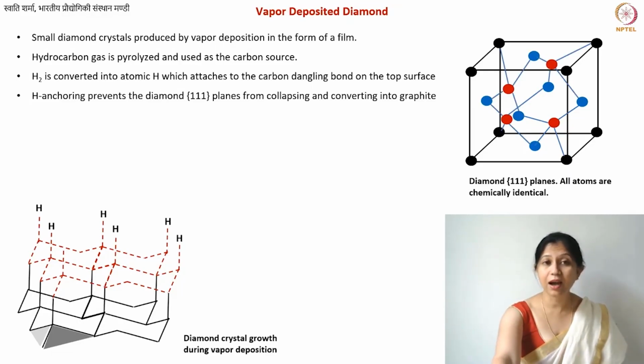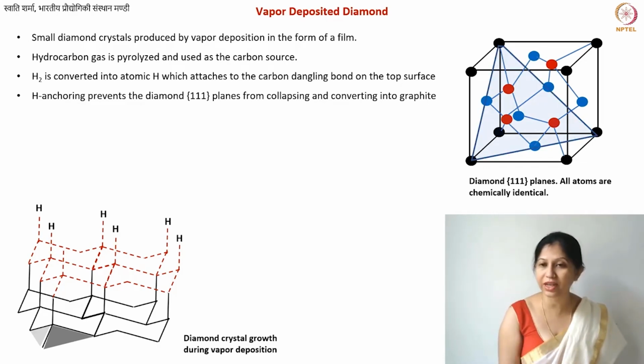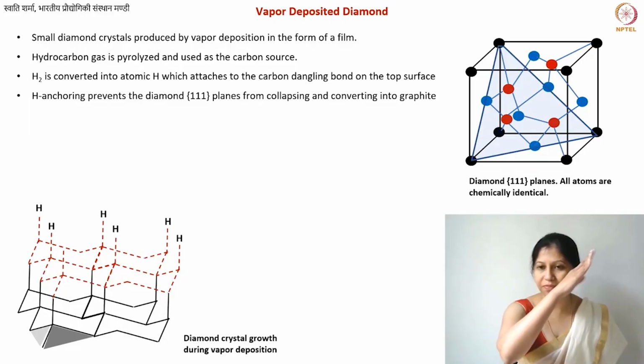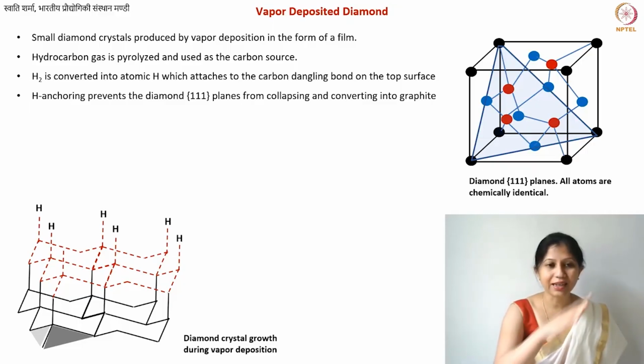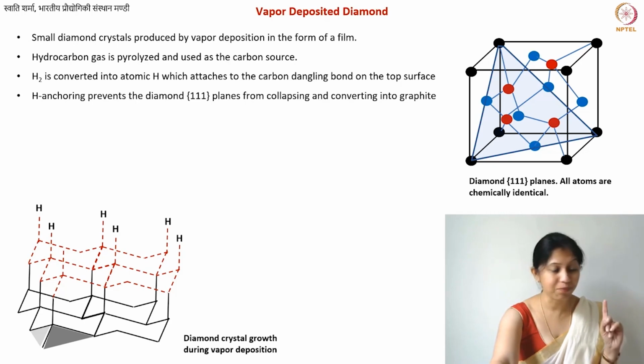I was talking about the 111 plane. You will take it similar to any other cubic crystal. So this is your 111. Basically, it is this diagonal plane, and when a diamond crystal grows, that comes as a facet. This facet will not exist; the structure will flatten out if you did not have the atomic hydrogen to bond with your 4th electron, which would possess sp3 type hybridization.